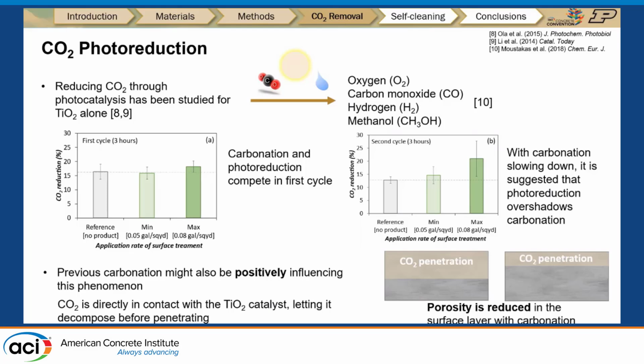Besides, we know that the previous carbonation might also be positively influencing this phenomenon. As the carbonation is happening, the porosity in the surface layer is reduced, so that the carbon dioxide is hard to penetrate inside the cementitious materials. It stays on the surface area and reacts with the titanium dioxide catalyst.